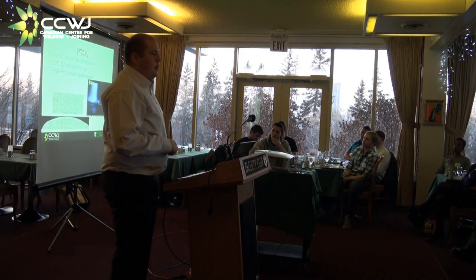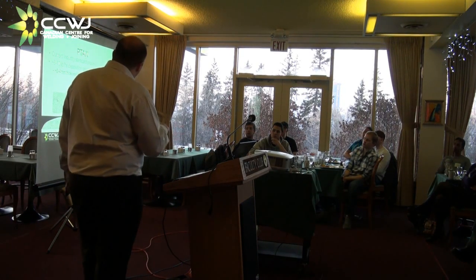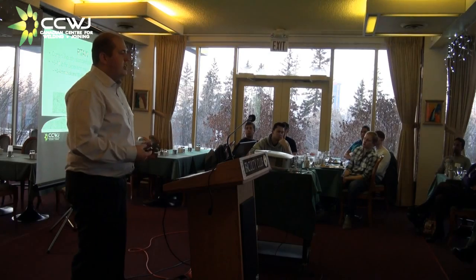PTA right now is the current method of choice for depositing these overlays. Basically, it's a TIG torch on steroids, for those of you who aren't familiar with it, and it uses a powder consumable. Here's a high-speed video we shot with our PTA machine in our lab. Here we can see our powders blowing in the rear of the arc, so the powders aren't experiencing the full heat of the arc and the weld, and they can survive welding.